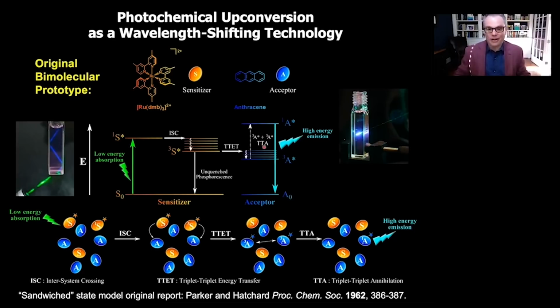That's triplet-triplet annihilation, TTA. You make the singlet, and as long as you have enough energy in the two triplets to put you on the singlet surface, you fluoresce out a photon. And that gives you these beautiful pictures that you see here and here, where you're going in with green laser beams and you see this beautiful blue light coming out, which is really the anthracene fluorescence.